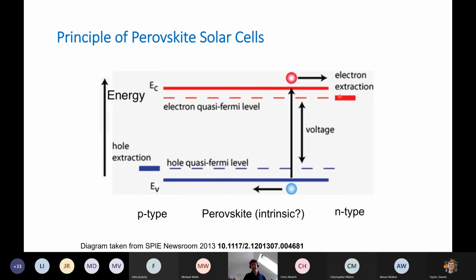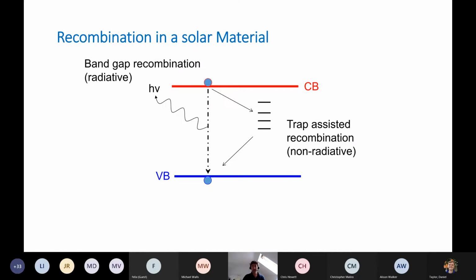When you connect it to an external circuit and the current flows, then you extract the charge, so they can't recombine. But when you leave it under what we call open circuit conditions and don't extract it, it's 100% efficient at re-emitting light. So that's a perfect solar cell. In reality, we have defects in the materials. The electrons can drop into traps or defects, and then they recombine without the emission of light or with lower energy photons. We consider that non-radiative recombination, and they are losses.